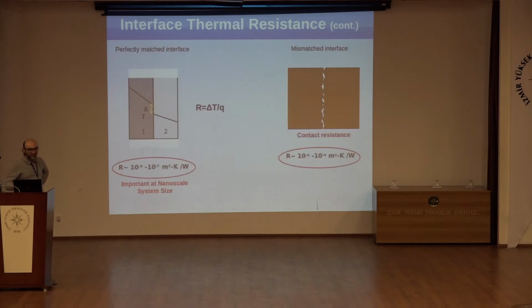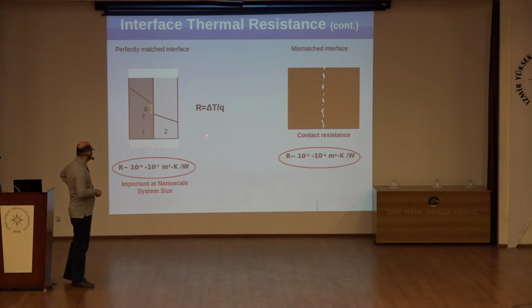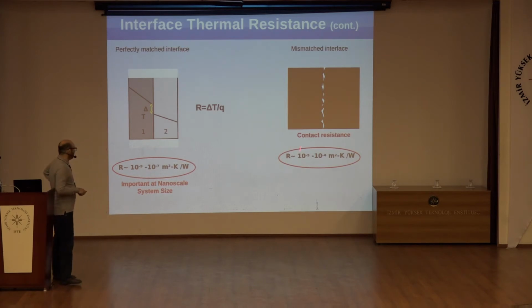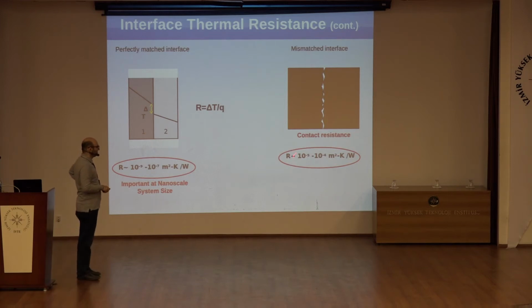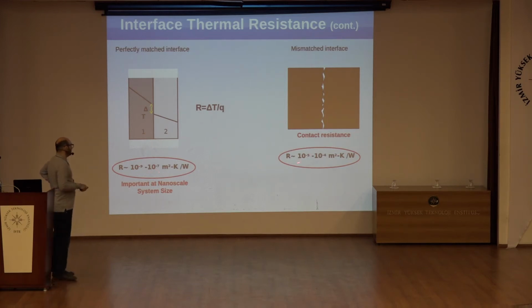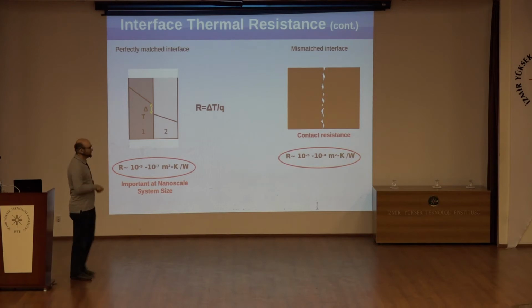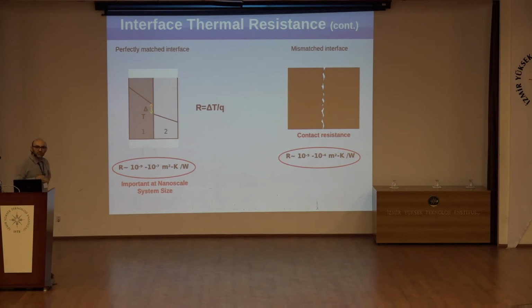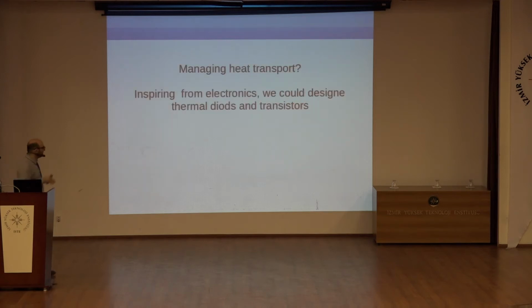and even large-dimensional systems. But when we come to nanoscale system sizes, it becomes more important, since it is different from what we have in macroscopic systems. It is what we call a mismatched interface, and it is called contact resistance. It is about 3 orders of magnitude higher than the amount of boundary resistance that I mentioned in the last slide. It means that when we come into lower dimensions, it is important to take into account all things as described by Ali, different kinds of scattering and so on.